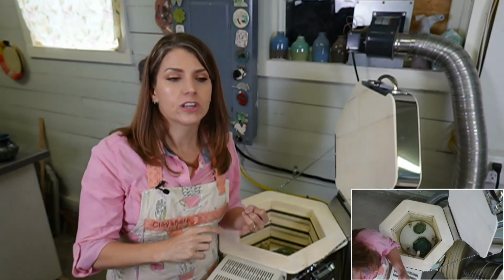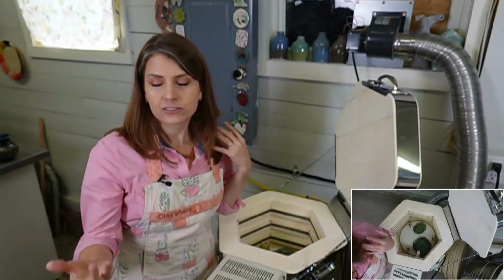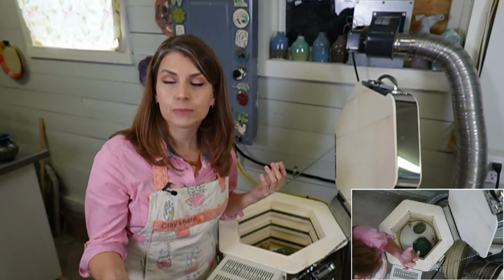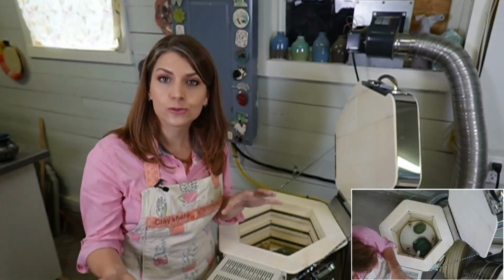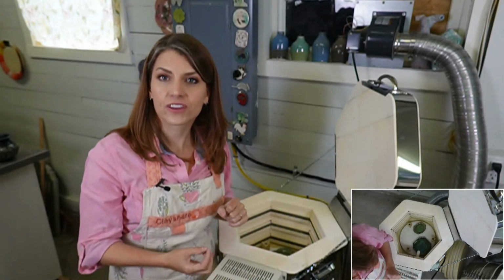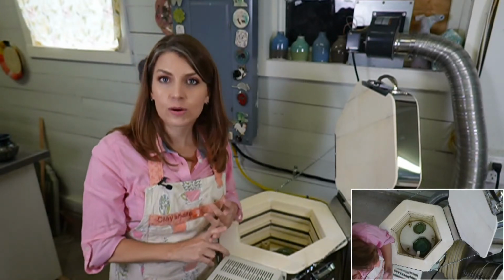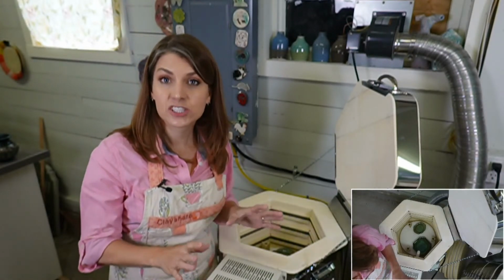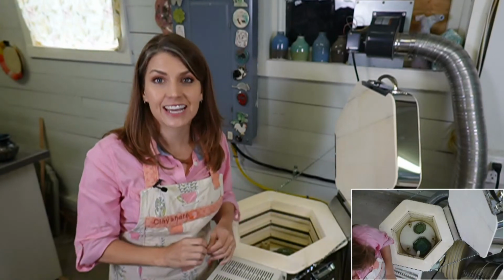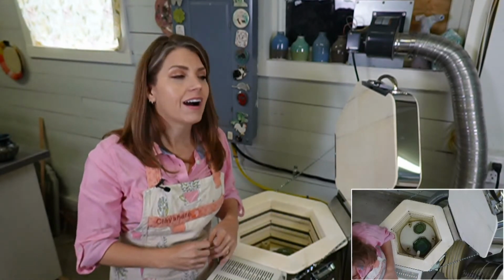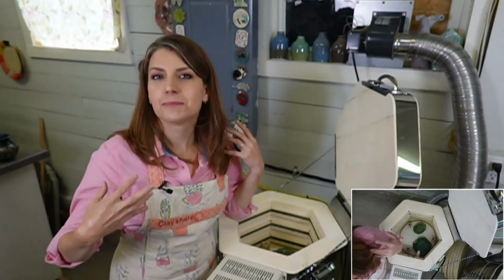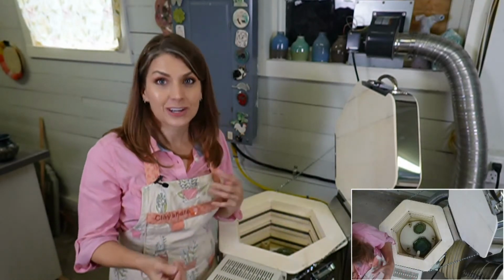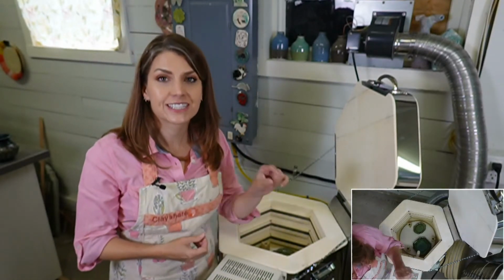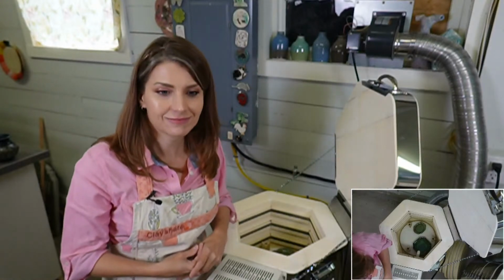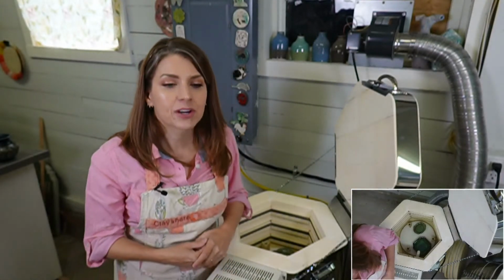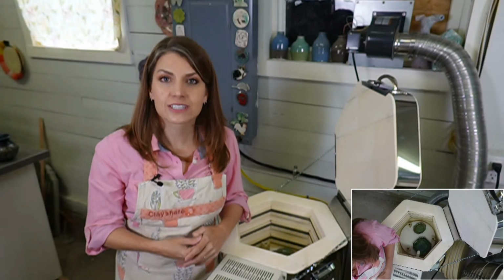When I'm teaching at schools, I usually do a little longer because people tend to make their pieces a little too thick, or they're not quite as dry as people think they are. So I'll do a 6 to 8 hour preheat sometimes for those. Kids projects, I always do a 6 to 8 hour preheat because I love working with children and they love to make really thick pots. So go a little longer on that preheat because it can save you from having an explosion. So you had the Amaco velvet stick to you at cone 6.